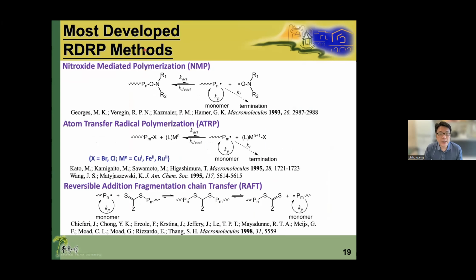In this field, there are three most developed methods: nitroxide mediated polymerization, atom transfer radical polymerization, and reversible addition fragmentation chain transfer polymerization. Nitroxide mediated polymerization is the earliest technique. They use the nitroxide species to deactivate the propagating radical and form the dormant species. By using this equilibrium, you can suppress the radical concentration. In radical polymerization, the polymerization rate is proportional to the radical concentration, but the termination rate is proportional to the radical concentration squared.